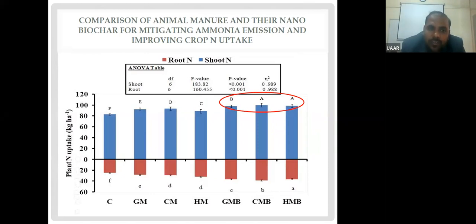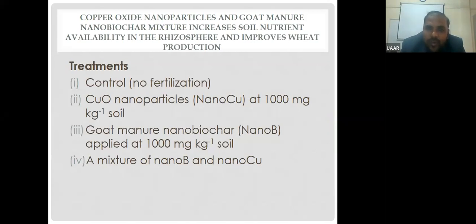In the next experiment, we used copper oxide nanoparticles and goat manure NANOBIOCHAR mixture to increase soil nutrient availability in rhizosphere and improve wheat production. There were only 4 treatments. One was control with no fertilization, and there was copper oxide nanoparticle, which was applied at the rate of 1000 milligram per kilogram of soil, which is equal to 1000 ppm. There was goat manure NANOBIOCHAR, which was applied at the same rate of 1000 milligram per kilogram of soil, and a mixture of NANOBIOCHAR and copper nanoparticle, each 1000. They were applied at the same rate.